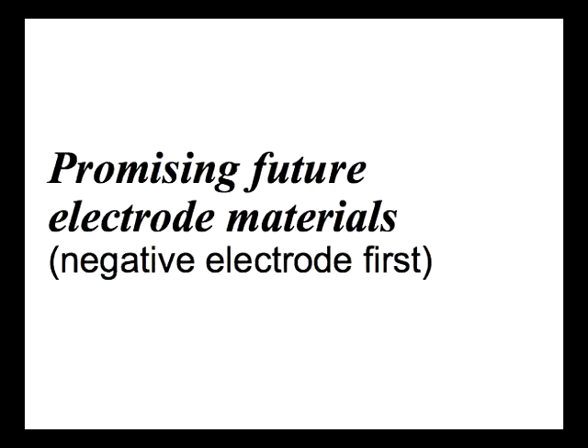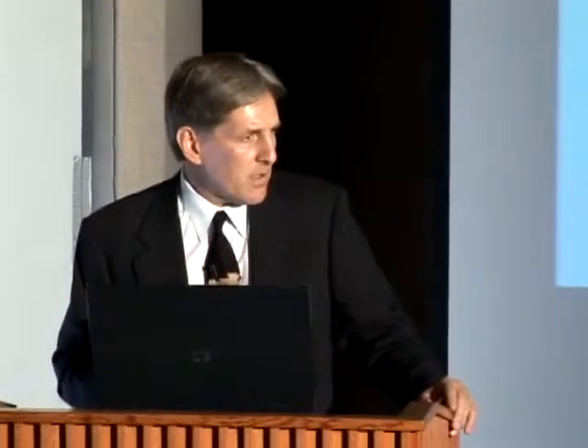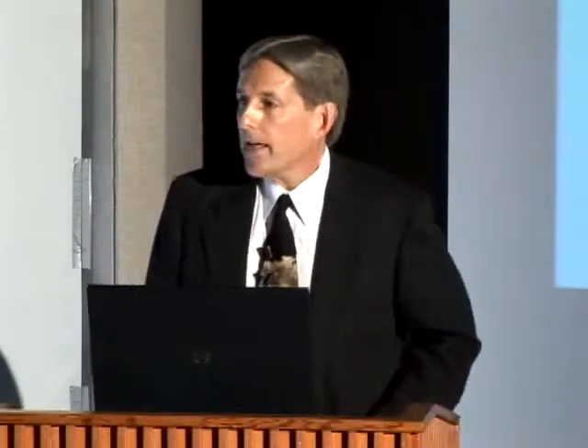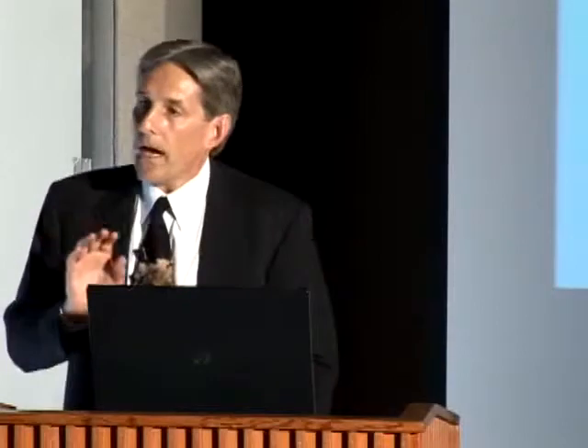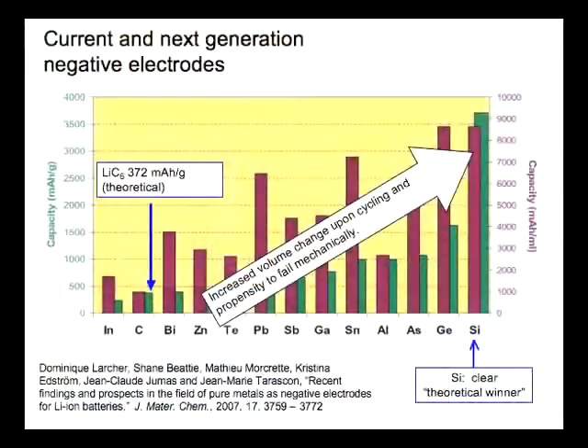I want to touch on some promising developments. I'm very optimistic about where batteries are going to go — they're likely to have a profound increase eventually in energy density. This is exemplified by an article from the group out of Bordeaux, CNRS laboratories. The capacity of most systems of interest for the negative electrode is plotted here. We're using today lithium carbon at about 372 mAh per gram — that's the theoretical value for LiC6.